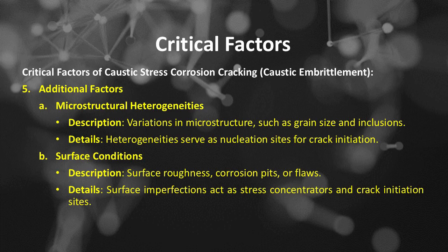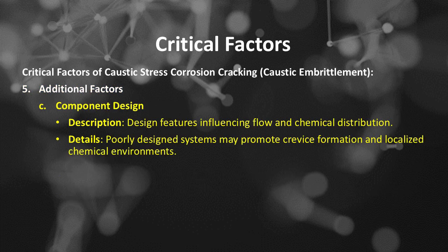Additional factor B, surface conditions: surface roughness, corrosion pits, or flaws. Surface imperfections act as stress concentrators and crack initiation sites. Additional factor C, component design: design features influencing flow and chemical distribution. Poorly designed systems may promote crevice formation and localized chemical environments.